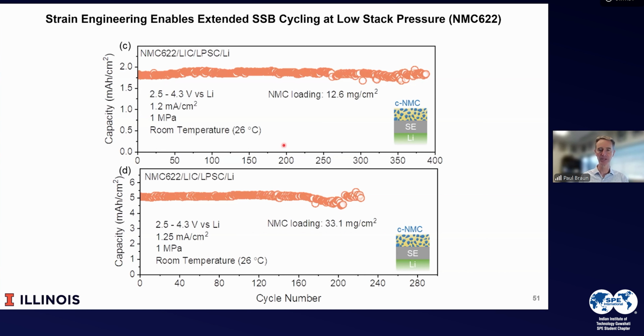We can do this kind of strain engineering for other systems like NMC, and we see indeed that by doing strain engineering, we can get very good cycling, much as we see in the LCO system. And so I think this is a generic phenomenon that strain engineering in solid-state batteries will enhance cycling performance, and any solid-state batteries should be made accounting for the chemomechanics of both the anode and the cathode.